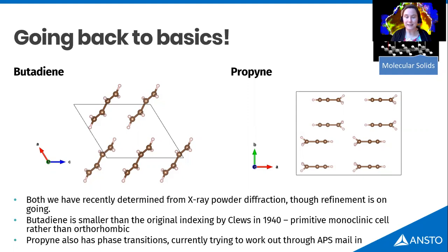Propyne is a little bit complicated. I should say one of my ways of approaching the structure solutions of these is to go find another structure where it's a co-crystal somewhere else, and then I use that as the basis for my rigid body, and then I add that and do simulated annealing in order to solve the structure. With propyne, there are no structures that I can find with propyne within it. So actually constructing the rigid body was sort of like a lesson to begin with. It was sort of like, arrange it a little bit and look at the bonding. Okay, that seems to make sense. And then feed that into the simulated annealing.